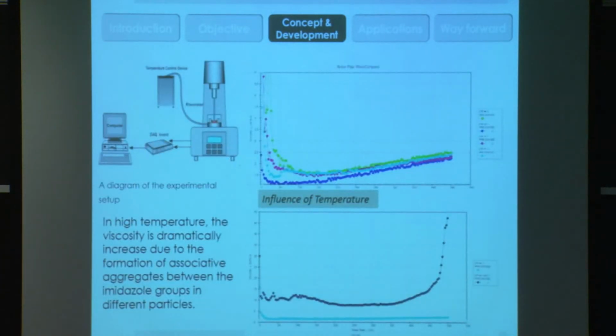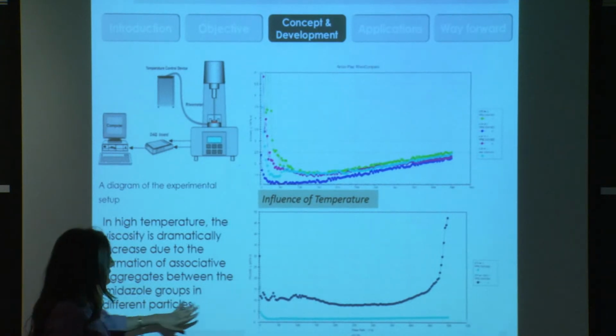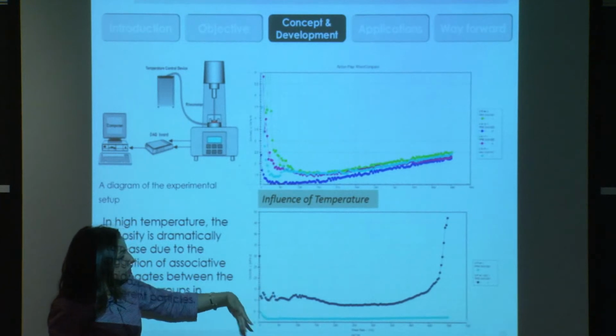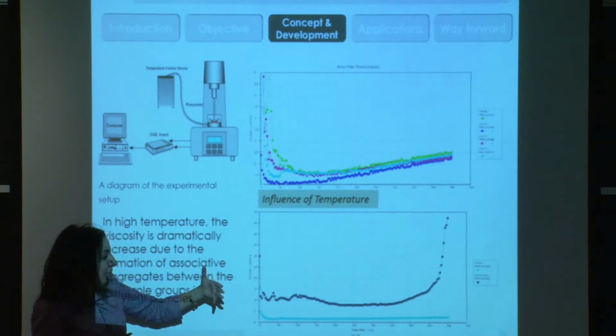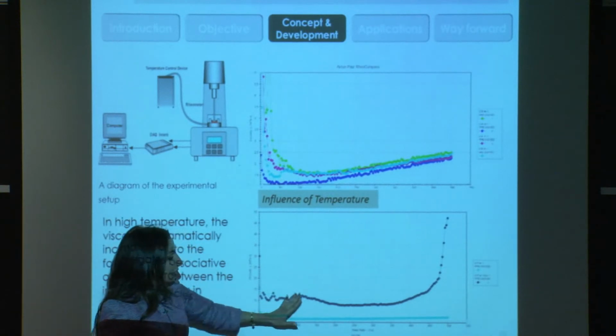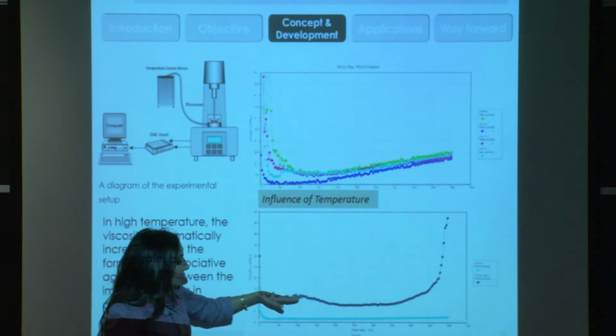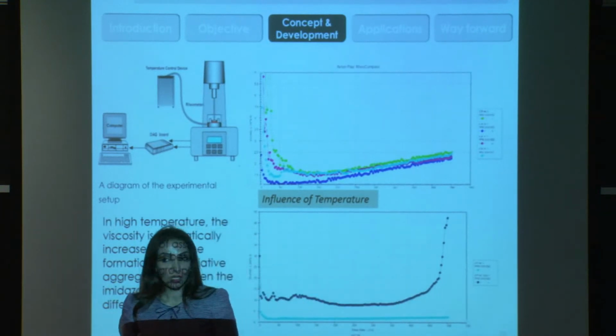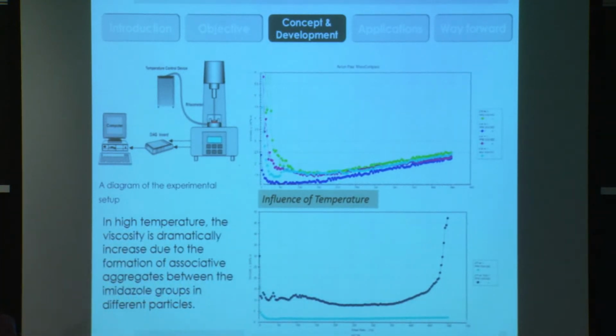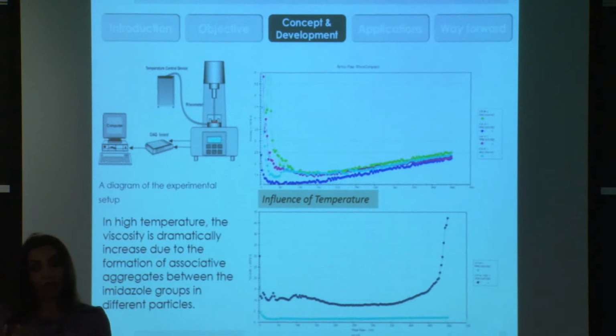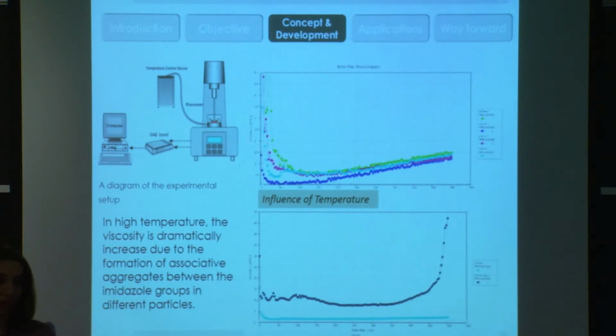And this is the results of our test. As you can see, here the proposed shear thickening tries to viscosify with high temperature. So as we increase the temperature up to 100 degrees, the viscosity is increased up to 100 centipoise with shear rate around 450. And this is an excellent result because, as we mentioned, our aim is to develop a shear thickening that can work in harsh environments such as high temperature.